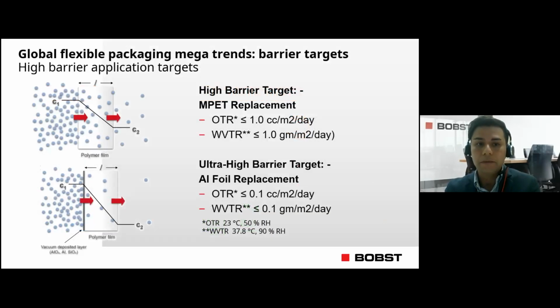This brings me nicely to a point on what are the mega trends for barrier targets. There are many depending on the different food segments, but we find for high barrier application, there are two targets. The first high barrier target is metallized polyester replacement at less than 1 cc per meter squared per day for oxygen, less than 1 gram per meter squared per day for water. The second is ultra high barrier target, where also it's considered as aluminum foil replacement, which is operating at 0.1 cc per meter squared per day and 0.1 gram per meter squared per day. Let's take a look at the solutions BOBST and their partners in collaboration have got on with regards to these two mega trends.